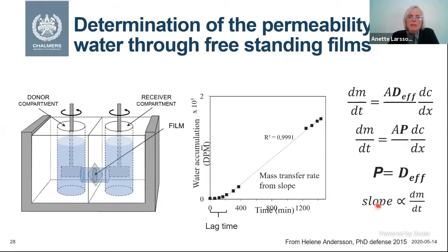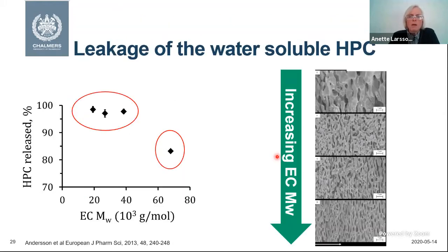And we tested the permeability in these diffusion cells. So we took the films, placed them here in between two cells, and have tritium labeled water on that side, and looked at how much tritium labeled water was received in the acceptor chamber, and we could take the slope, and the slope is then proportional to the mass transport and the permeability, and that is approximately equal to the effective diffusion coefficient. And this diffusion process then will depend on things like the porosity.